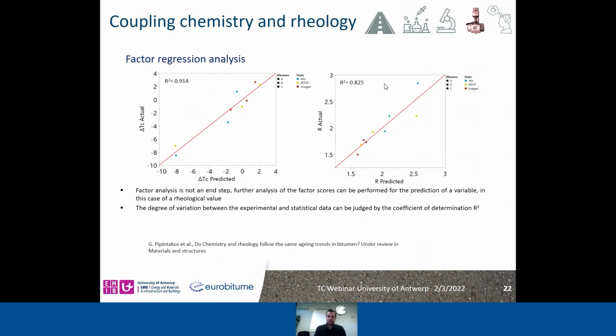Here in these two graphs, you can see, for example, the predicted value from the statistical framework for one of the rheological parameters that I mentioned previously, the delta TC, and the actual one that was measured from DSR testing. For both, the best correlations were observed. Also for the same parameter R, which shows the width of relaxation of your master curve.